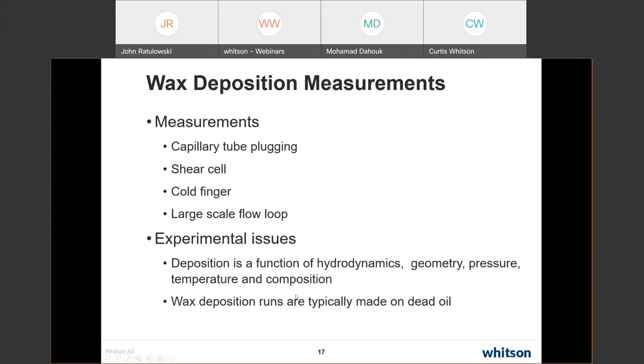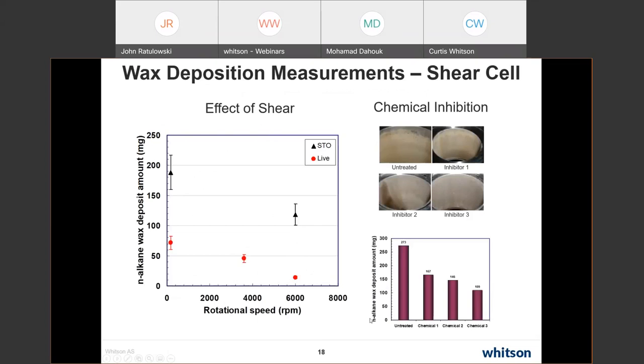So this is just to show you some deposition data. This is in the shear cell. And what we see in the shear cell is that the dead oil deposition rate is relatively high as compared to the live oil. This is a live oil sample. And that would be expected because by adding the gas into the system, you're depressing the wax appearance temperature, which also depresses the deposition rate at the surface.